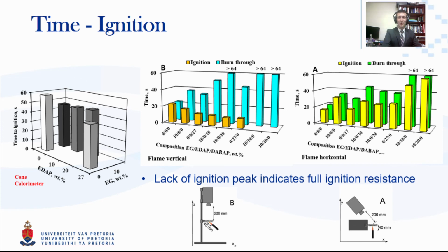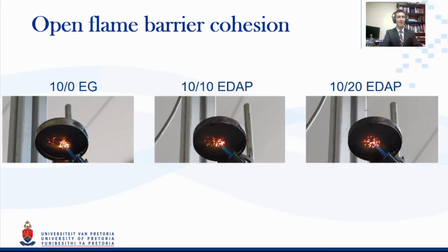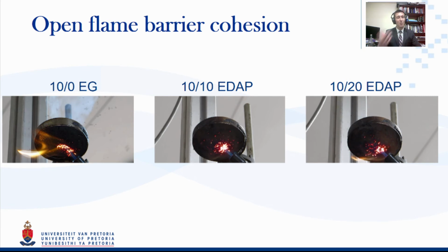So on the next slide, I'll show you guys the great result from below for the ethylene diamine. Expandable graphite on its own is on the left, and if you look closely, you'll see there are little particles flying around. These particles are expandable graphite pieces and pieces of material that are simply igniting and flying around and causing increased failure, whereas in the other materials, it almost looks like nothing's happening, but they've actually just continued burning until they eventually sag. And this is quite a good result, because the flame, although one can see the flame, never actually starts burning on the surface itself.